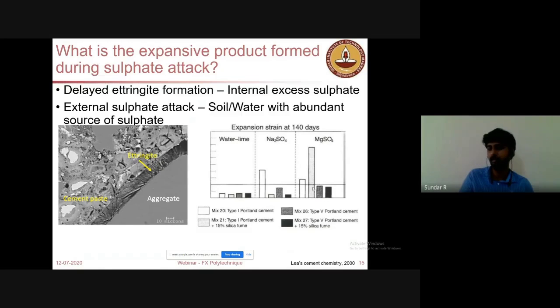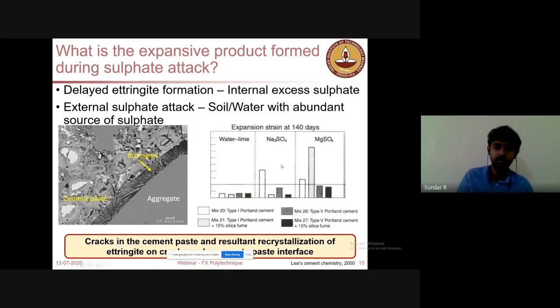When there are a lot of smaller pores and ettringite forms, there will be a lot of cracking, and that will create expansive stresses. So due to that, there is a problem. However, when we use sulfate resisting cements, that is type 5 cement, you will always have an expansive strain which is well within the permissible limit. This was explained here. As a result, you could see the cracks in the cement paste and recrystallization of ettringite causes the deterioration. So this is one form of deterioration in concrete.